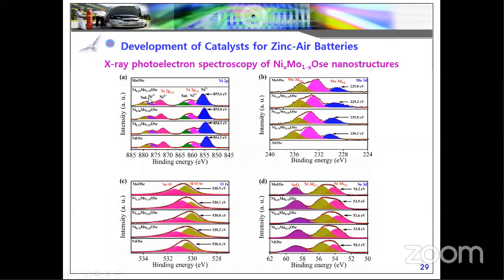When we change the ratio, the XPS also shifts. Compared to the other ratios, our optimized ratio has higher binding energy. From the studies, we can say our optimized material has high binding energy with nickel and molybdenum. In the case of molybdenum, compared to pure molybdenum selenide, our compositions have higher binding energy when we dope nickel at different ratios. In the case of oxygen, the bimetallic selenides show lower binding energy compared to the monometallic nickel oxygen as well as molybdenum oxygen selenides.